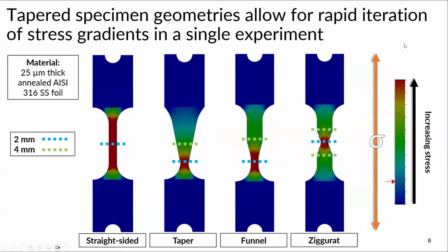So here's really the meat of the project. These are the tapered specimen geometries that we've designed, and that's to accelerate the testing of these materials. The first iteration was the straight-sided, which means we can only do 1 temperature and 1 stress, and that took 7 days. So it is an expensive, time-consuming method.